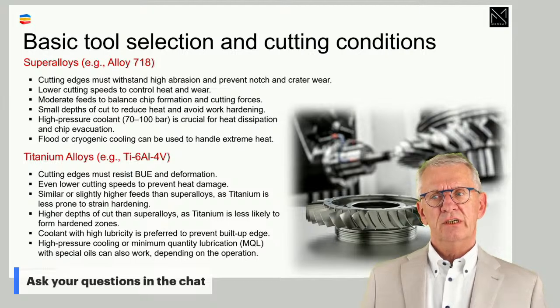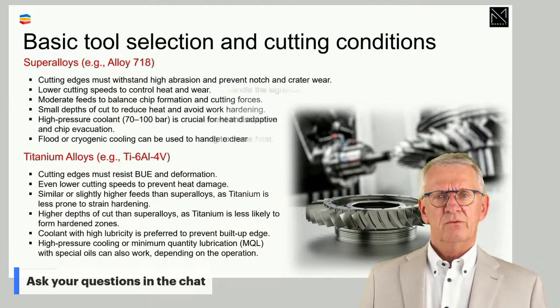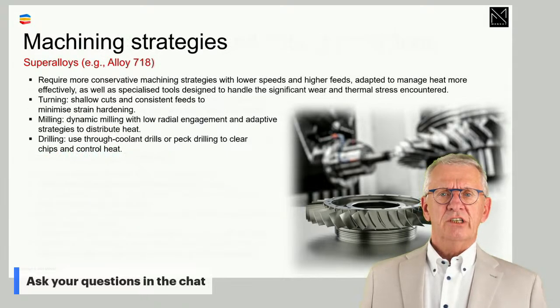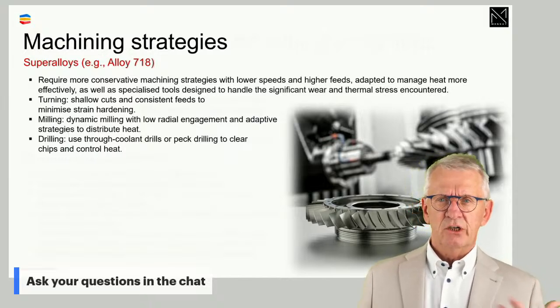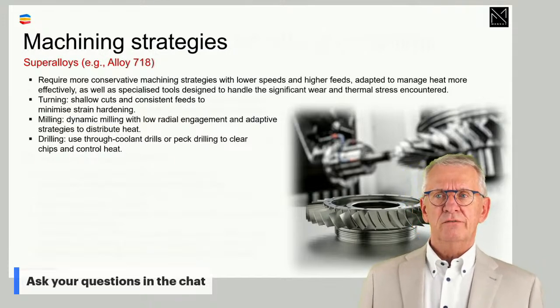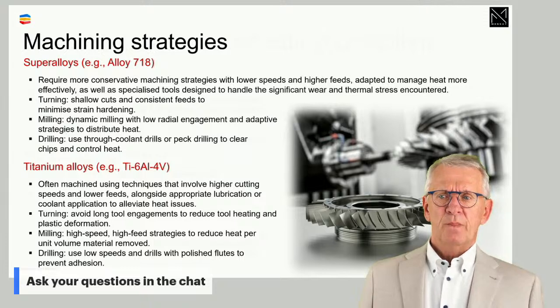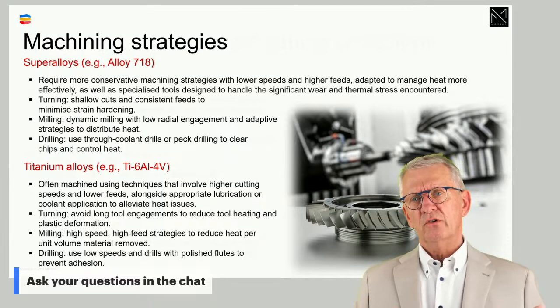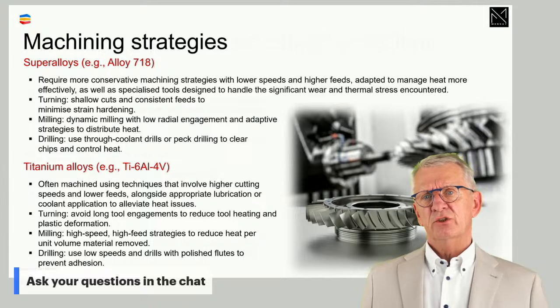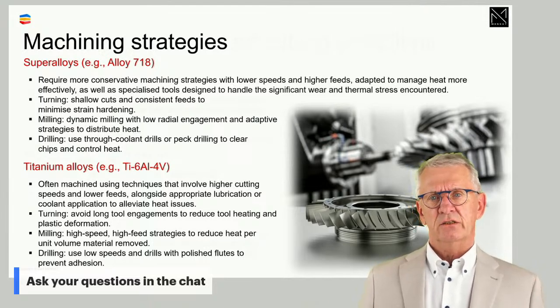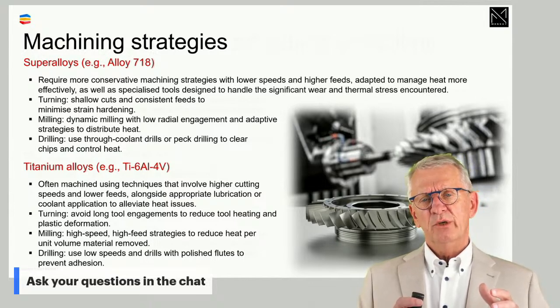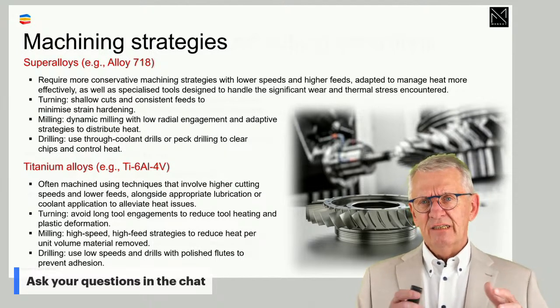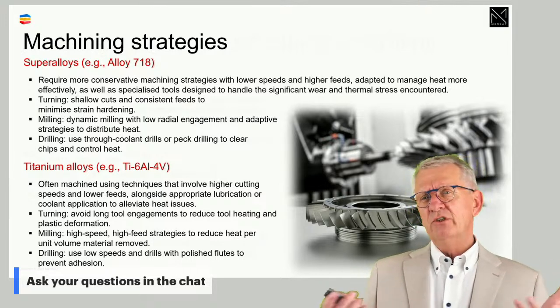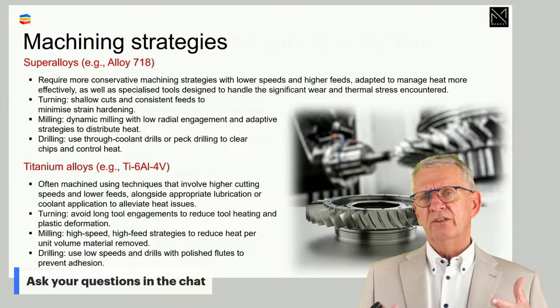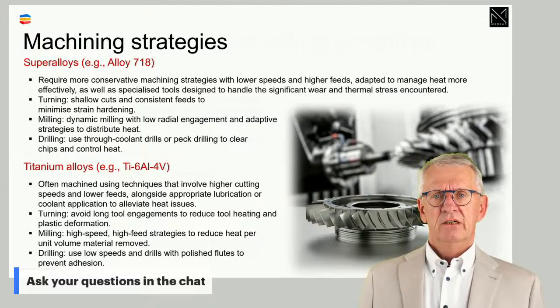Superalloys, high pressure cooling systems are interesting. Titanium, it's more about lubrication. That is what we have to be careful about. Superalloys, I would say it's the more conservative machining strategies with the lower speeds, higher feeds that we go for, while in titanium alloys, there we can use, or we are closer to the more typical high-speed machining systems. It's not the high speed like we know in steel and so on, but it goes that direction. So superalloy, when you talk about machinability, machining strategy stuff, I would say it's very vague now, but I would say go for high feed approaches, where for titanium alloys, high speed, high feed methods, or machining strategies, are a